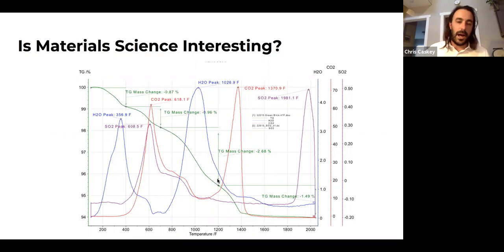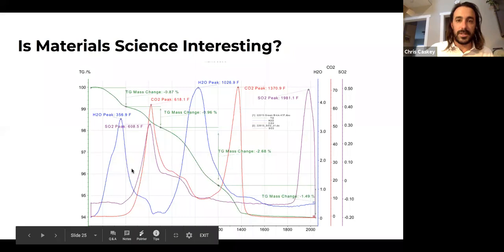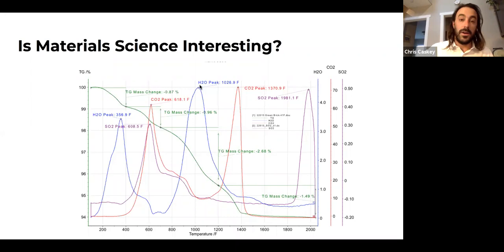So you're losing water, obviously. Here's a water peak, because it's never fully dry. Here's a water peak for some of these minerals that are actually hydrated. You're burning out CO2. This is like leaves, decayed leaves and fish poop. And then you're burning out CO2 again, and this is a carbonate decomposition. And then we have sulfur coming out as sulfur oxide as well.